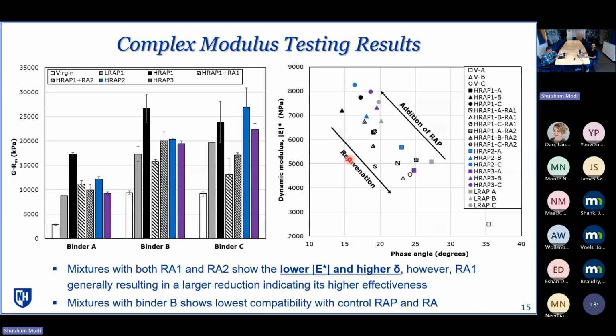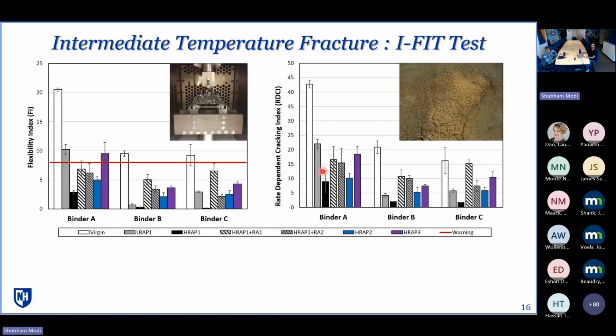and higher delta value, showing the improvement, whereas RA1 is generally resulting in larger reduction, again supporting the results from the binder side that we observed and showing higher effectiveness. And mixtures with binder B show the lowest compatibility with control RAP and RAS.